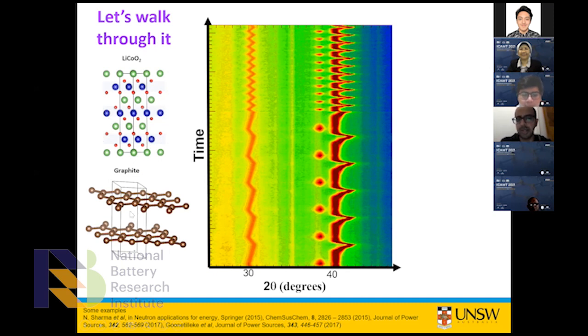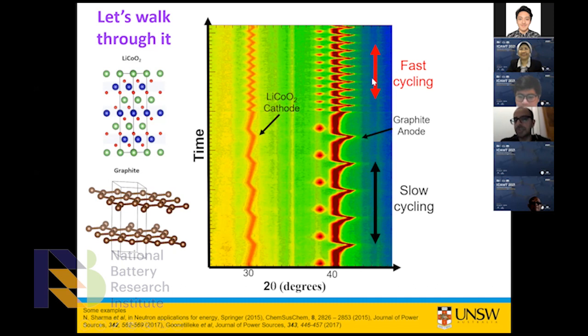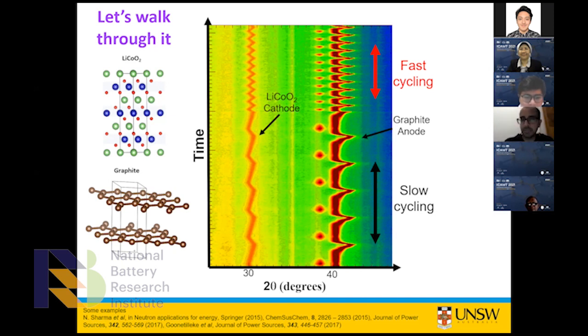With lithium cobalt oxide it's a solid solution reaction — it just expands and contracts as you charge and discharge. For graphite, similar expansion and contraction, but with a two-phase reaction where you nucleate a second phase. If you go slower in graphite, you see staged intercalation. You can get both structural information and kinetic information — how fast the structure changes as a function of how much current you apply. If you double the current, does the structural change double, or is it less?